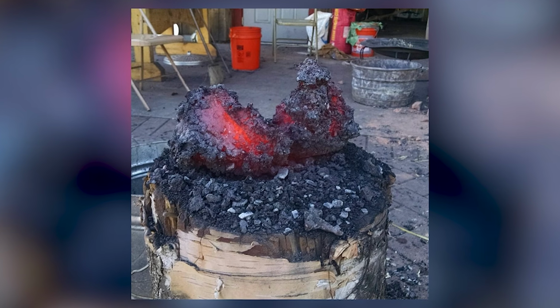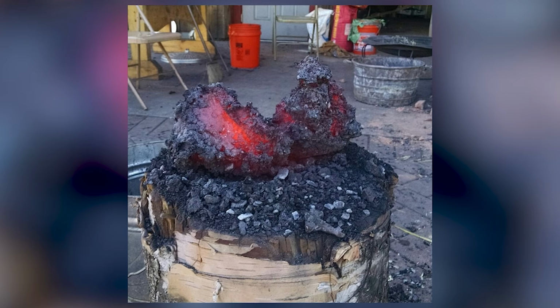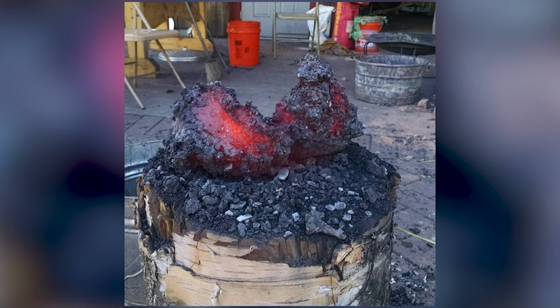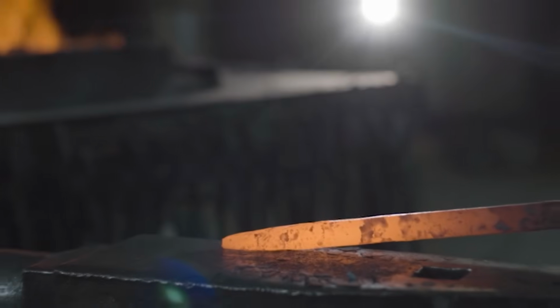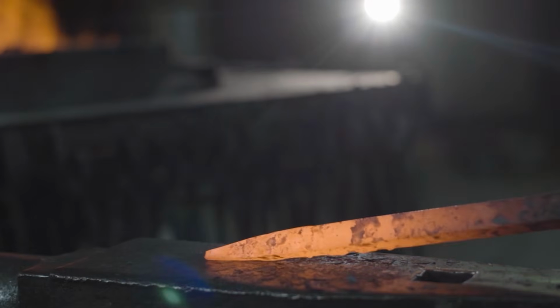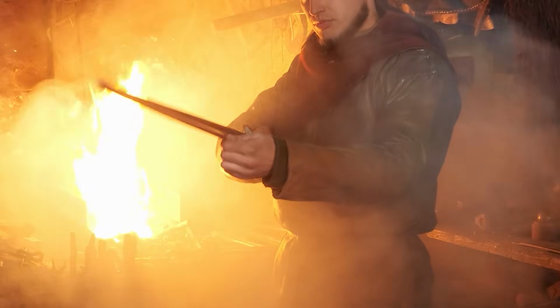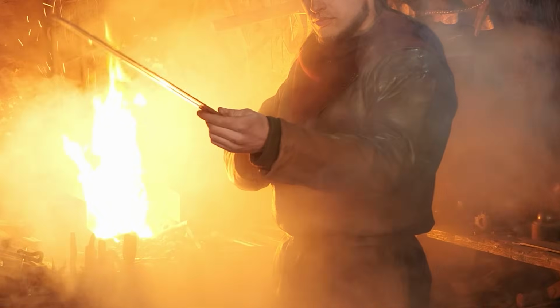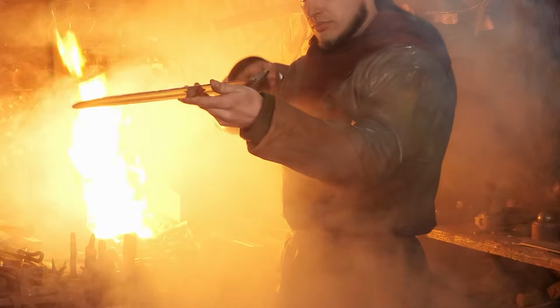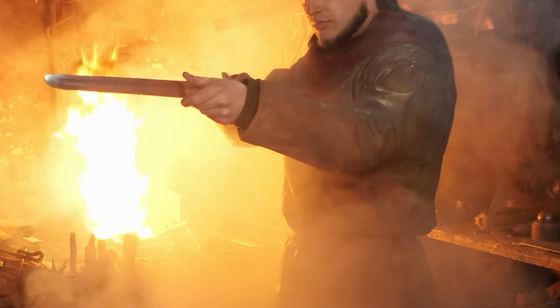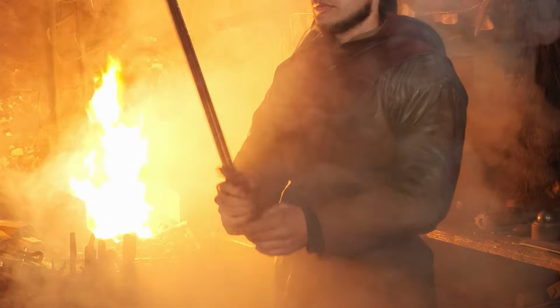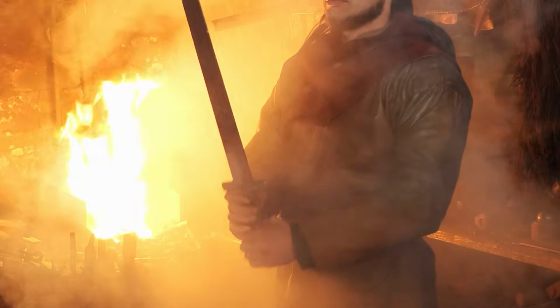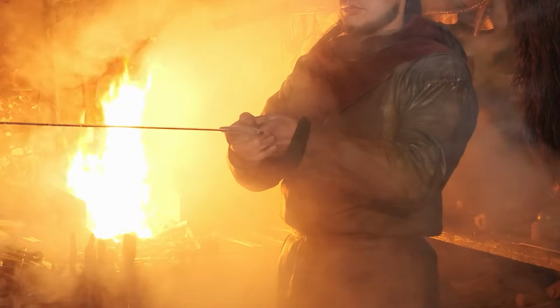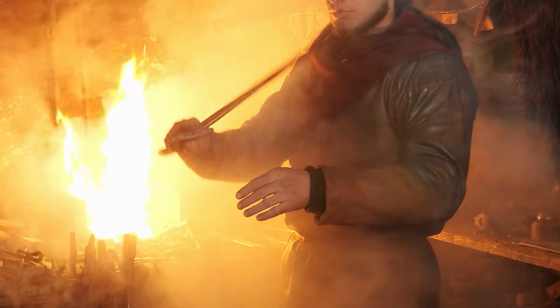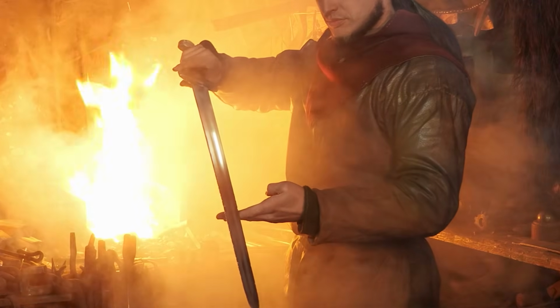These pieces were forge welded together, heated to white-hot temperature. Their surfaces would begin to liquefy. A few hammer blows, and they fused permanently into one. The result was a blade with a hard edge that held sharpness, supported by a flexible core that absorbed impacts without shattering. This composite structure, hard edge and tough body, was not a single material trying to be two things. It was two materials, each doing what it did best.